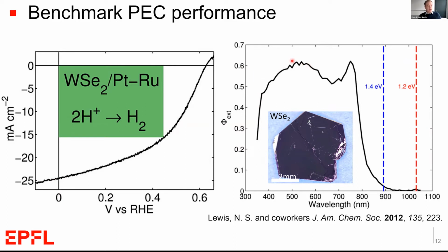This is another metric that we use in our lab to measure the performance or quantum efficiency of the photoelectrode as a function of the illumination wavelength. So different wavelengths of light have different performance. And what this says is that at 500 nanometer light, about 60% of the photons that are absorbed by the electrode are converted into hydrogen, right? So that's a pretty good performance for this single crystal photoelectrode. But still too expensive. We'd like to find a way to get similar performance, but using inexpensive solution-based processing techniques.